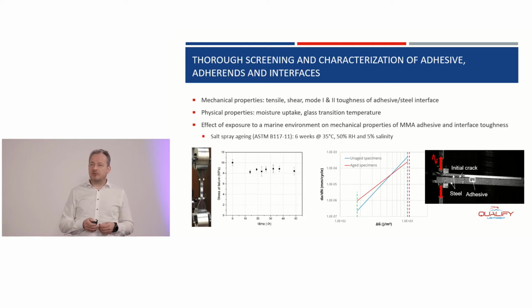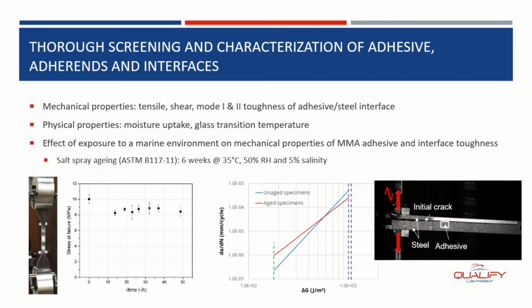So looking at the material level, it was performed to, on the one hand, characterize all the constituents of the joints that can help as an input to the simulations, but it also helped us to evaluate the performance of these materials under both unaged and aged conditions. So we looked at both mechanical properties, conventional mechanical testing in tensile shear mode, looking at the interface properties, toughness-related properties. We looked at physical properties like transition temperatures, like moisture uptake.